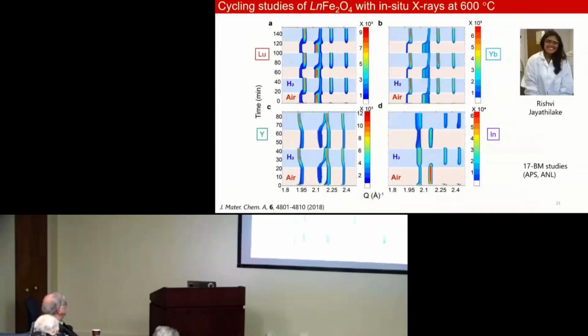My student Rishvi, I decided to put Rishvi in here because she's such a fan of Bob and wanted to take that picture. This is the work that she did on these 2-1-4 materials using in situ synchrotron X-rays. This is an example of cycling at 600 degrees Celsius, where we took air and hydrogen. We look at certain peaks and at how the A site behaves. I said it has to be rare earth. Actually, it doesn't. You can put an indium, for example, on that site. It just has to charge balance.